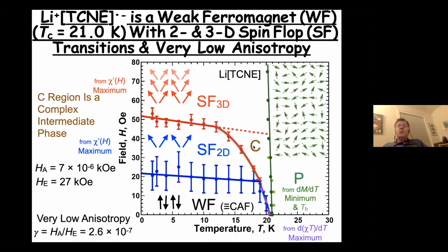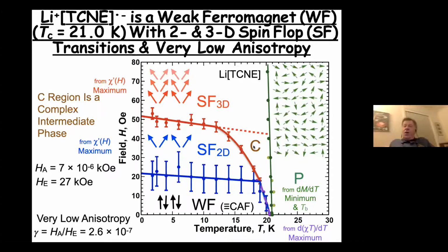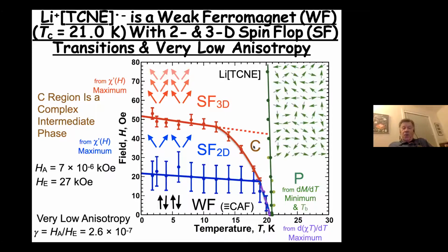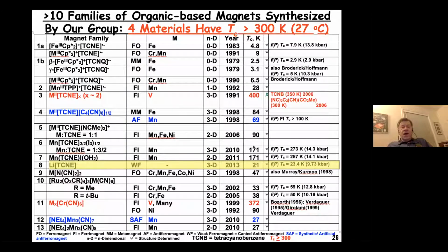So this is an exceptionally weak, as you would expect for a first row element-based magnetic material, with lithium, of course, being even lower mass than carbon and nitrogen, the other elements for this material. So just to summarize, our group has made over 10 families of magnetically ordered materials with several examples above room temperature.